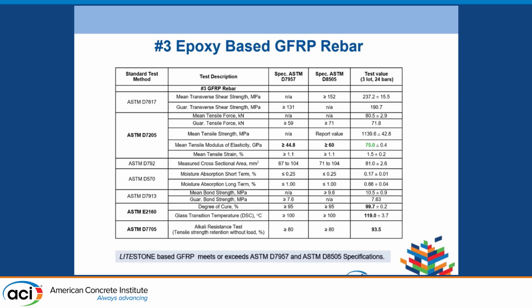Here we show the data for the number 3 epoxy-based GFRP bar. The tensile modulus is about 70 gigapascal, and the tensile strength is about 1,000. And the degree of cure is near 100%. It reflects the fast reactivity of the system. And the alkaline resistance test showed the tensile strength retention is well above 80%, which is the requirement. Overall, the LITESTONE system-based GFRP rebar meets or exceeds the current ASTM D7957 and ASTM D8505.